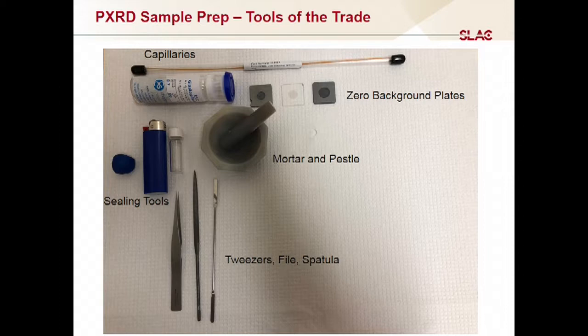But a couple of considerations that I just want to mention. One is, how do you pick the depth of that well? This is sample dependent, because if you're using one of these, you typically want to work in a theta 2 theta geometry so that the illuminated volume doesn't change. And that gives you very nice data. But the problem is that the theta 2 theta geometry assumes an infinitely thick sample. So if you have something very light, something carbon-based, you actually need quite a bit of depth before it becomes infinitely thick. The X-rays will penetrate down to the bottom of that pretty easily.